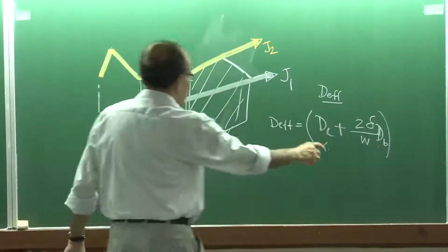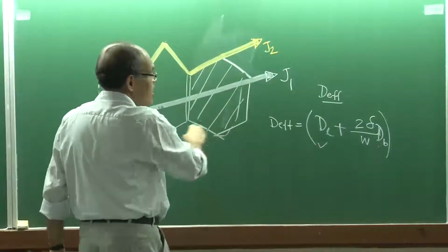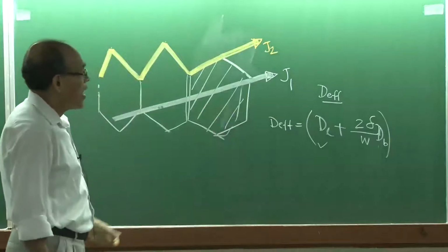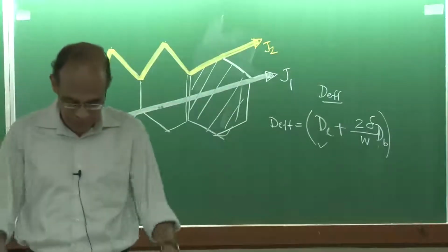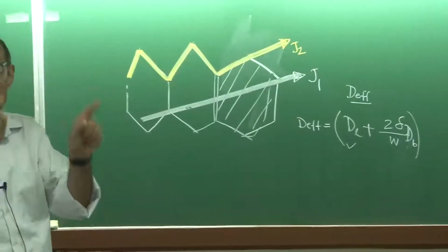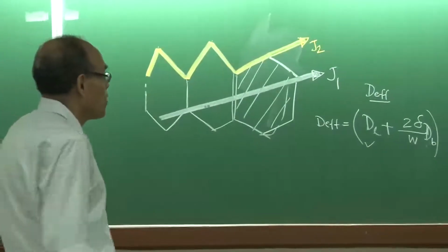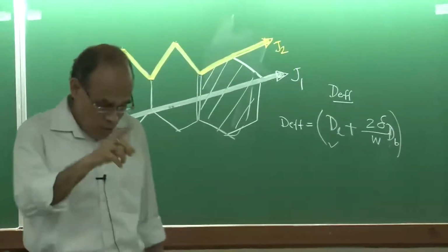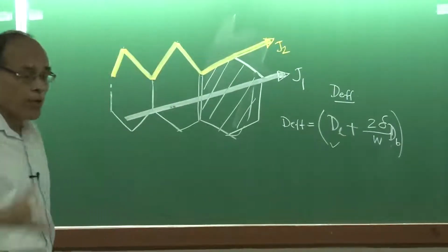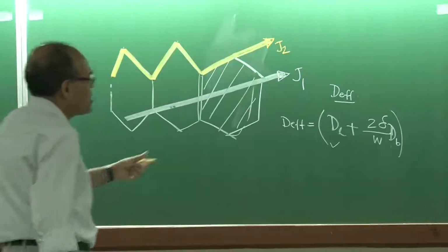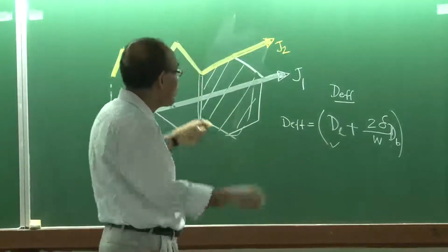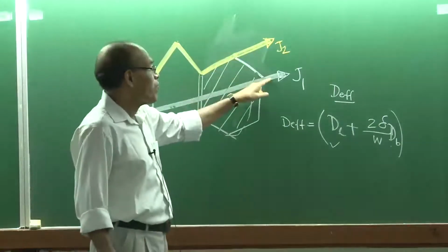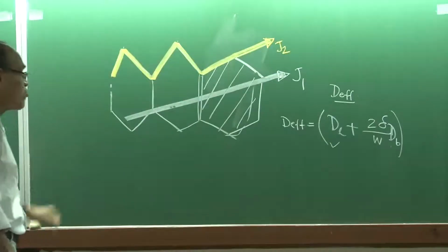Now this W, as I have indicated, is an average linear dimension of the grains, and in the context of that idealized demonstration where I have drawn a 2-dimensional square grain, W was taken to be one of the linear dimensions. If you would have considered a spherical grain, you could have taken W to be equal to the radius. So it's a very simplified analysis just to explain the significance of the parallel fluxes that we have tried to address.